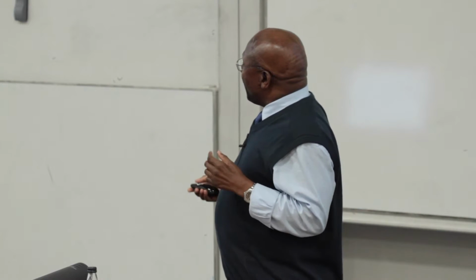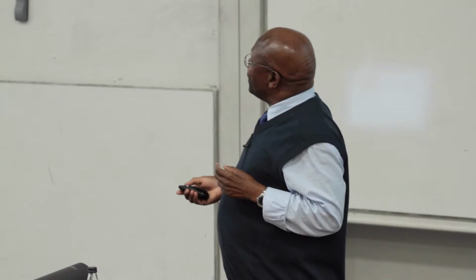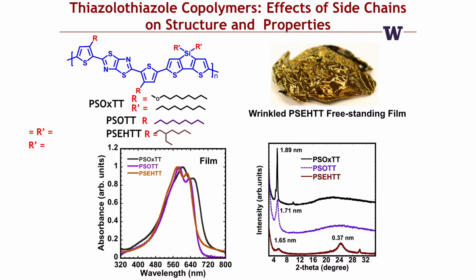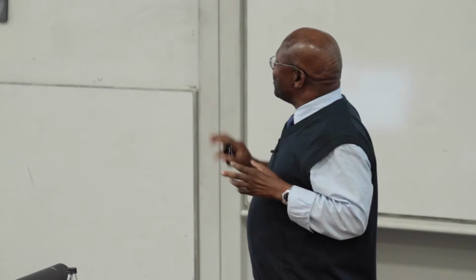And in this way, we discovered one polymer and relatives in particular. The structure is shown here. This is the backbone of the polymer, and we have different side chains attached to it. And this is what it looks like, a very wrinkled freestanding film. And of course, we can deposit more uniform films by spin coating. This was just cast to look at the characteristics of the material.